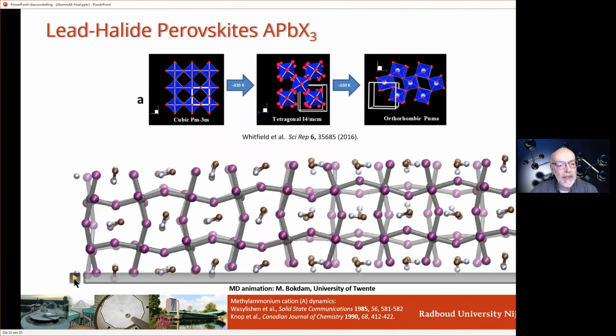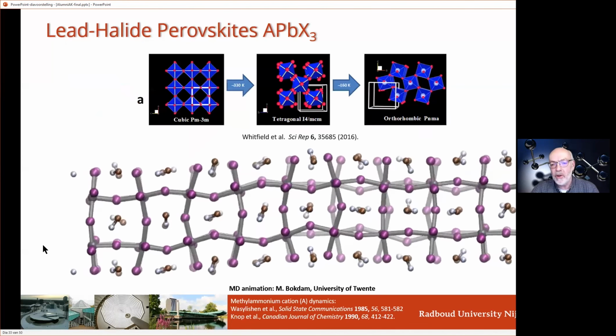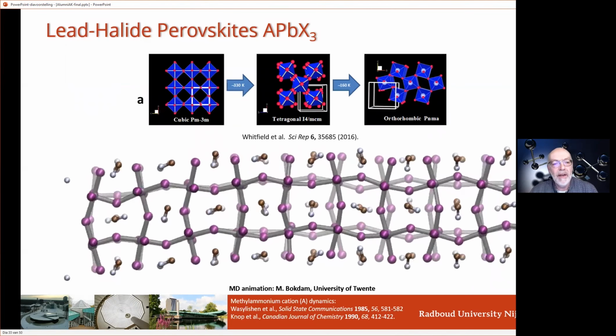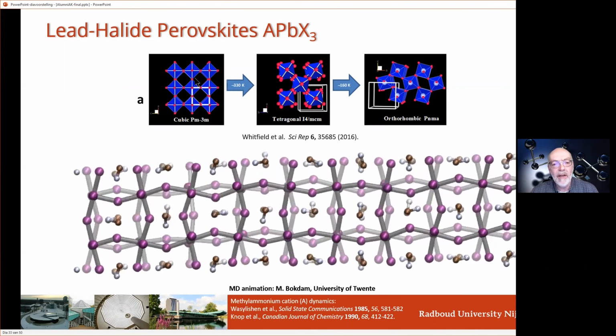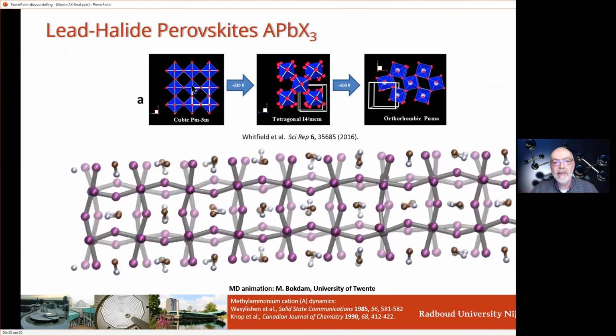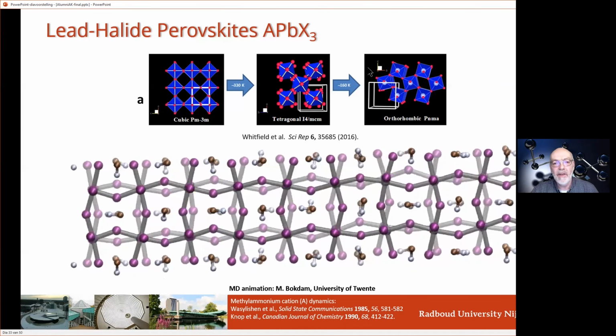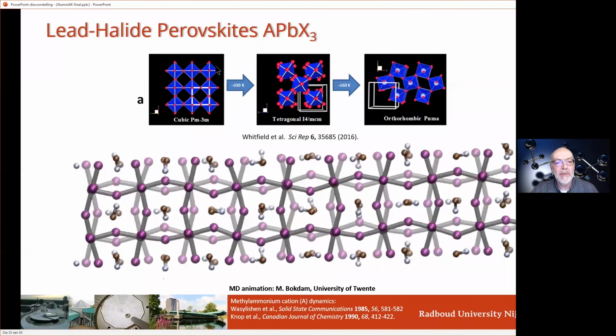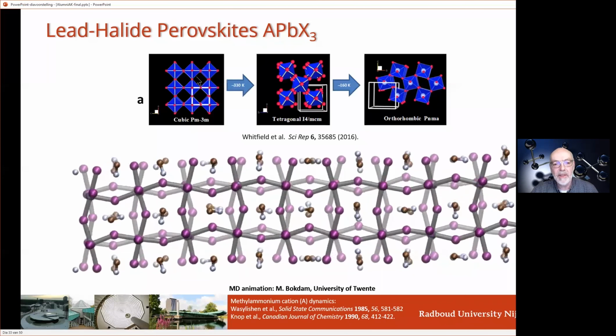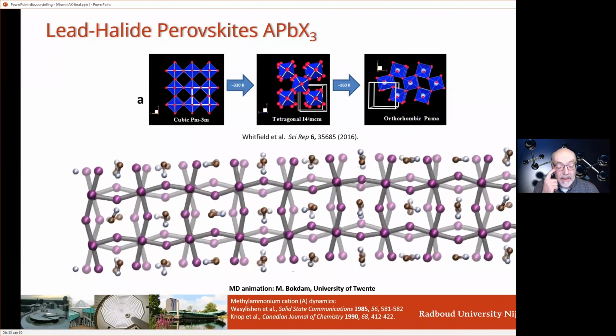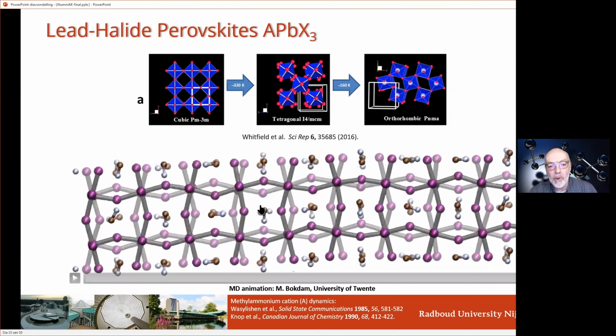And the whole issue is that they are super dynamic structures. So you have interesting phases. You have lead iodide octahedrons. And there are different phase transitions. The interesting material is the cubic phase at higher temperature. The regular material actually is not cubic at ambient temperatures, but by playing with the composition of which cations you put in there, you can force it to become cubic, which is quite intriguing.